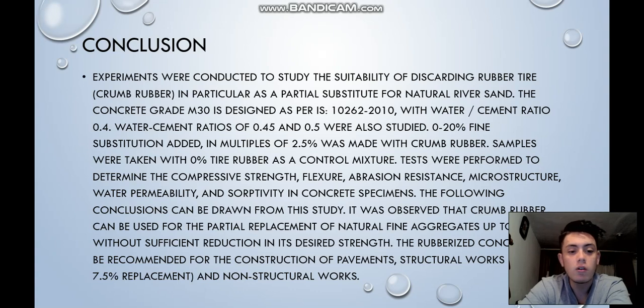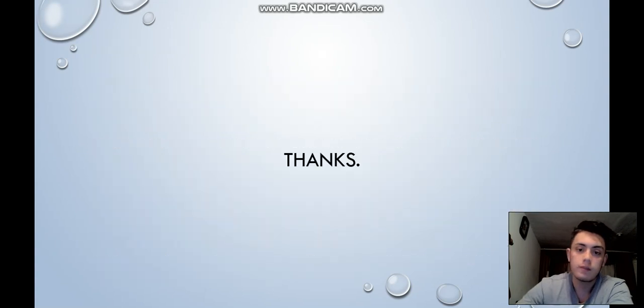The following conclusions can be drawn from the study. It was observed that rubber can be used for the partial replacement of natural fine aggregates up to 7.5% without significant reduction in strength. The rubber concrete can be recommended for the construction of pavements, structural walls, and non-structural works. Thanks.